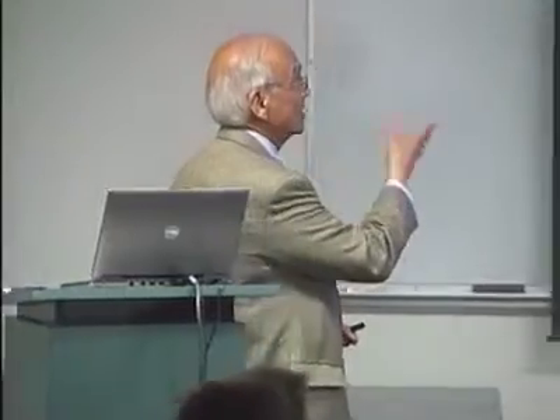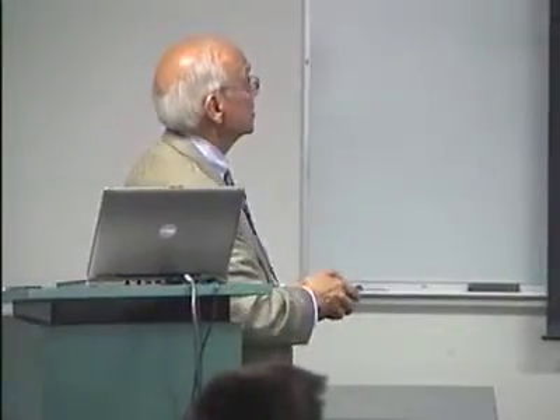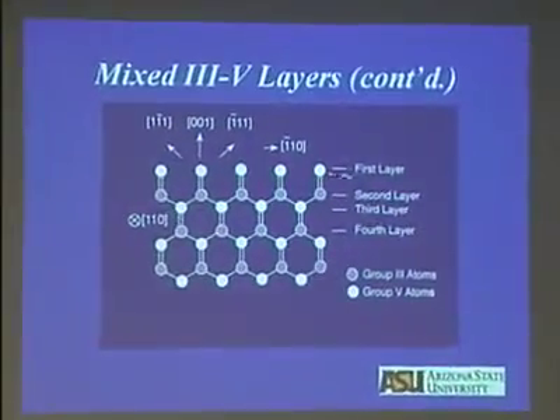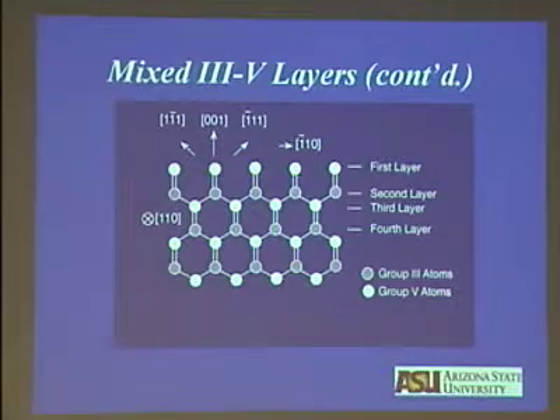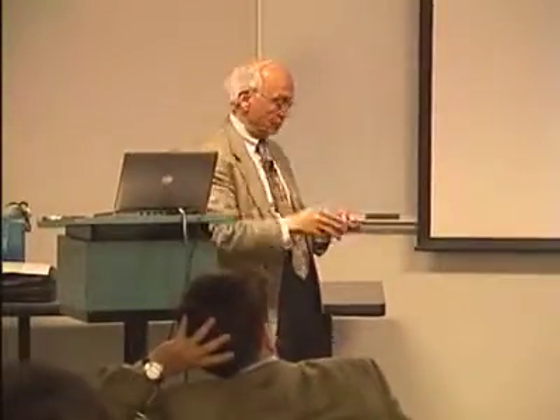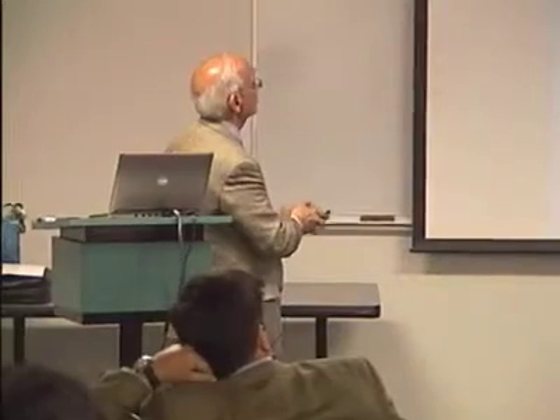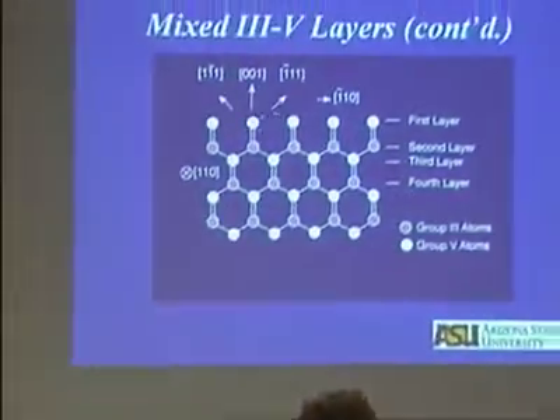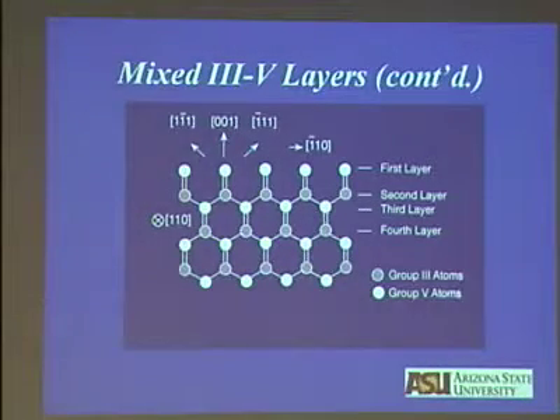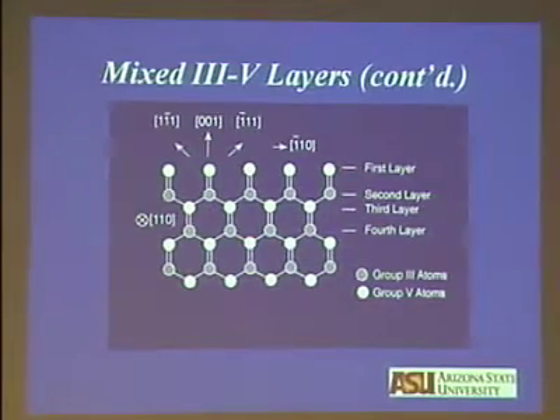Now, this is a schematic illustration of what goes on in the material. You are looking at the cross-section of the zinc blende lattice along the 110 plane. The first layer is the group 5 atoms, right? And the second layer is the group 3 atoms. Now, when you grow on this layer, you grow a bilayer. You grow group 5 and group 3 together, for the stability of the structure. The first layer is group 5. You will attach a group 3 layer here, and the atoms will phase separate, going into that position. Then if I have arsenic, you get a group 5 layer, and the whole process goes on.